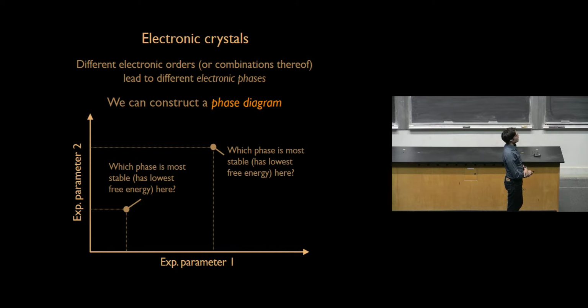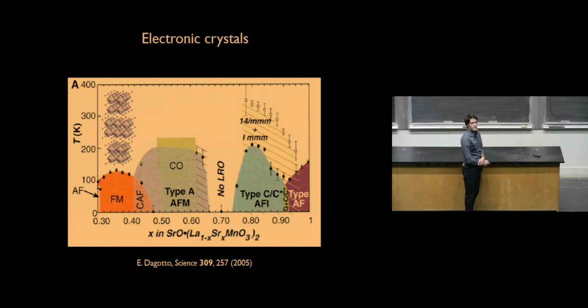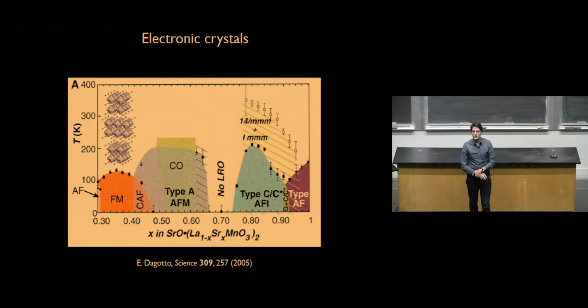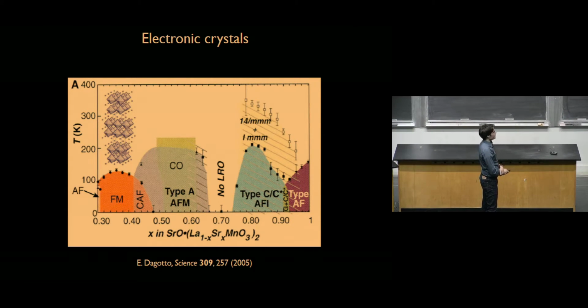So the question is, what is the electronic phase at each point in this plot? We go here and we ask ourselves, which is the electronic phase that's more stable, has the lowest free energy, if you like, at this point, and which is the electronic phase that's more stable here. And then we construct plots that look like this. So this is the case for manganese oxide. This is a manganese oxide perovskite, so it's a manganite crystal.